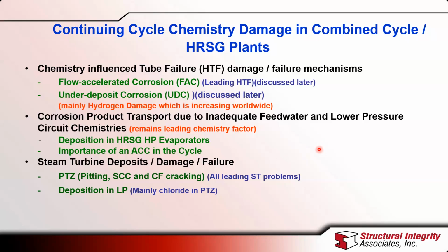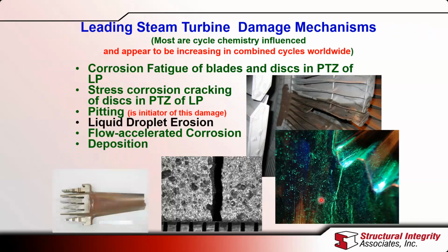Here's just an indication of the damage that occurs in the steam turbine. I just show this because I'm going to deal with the tube failure mechanisms in detail. The two main ones that take place are corrosion fatigue of blades and discs in the phase transition zone of the low pressure turbine, which I'll explain, and stress corrosion cracking in the discs of these. You'll see some of the pictures here. I'll talk about a few of these in a little bit more detail.